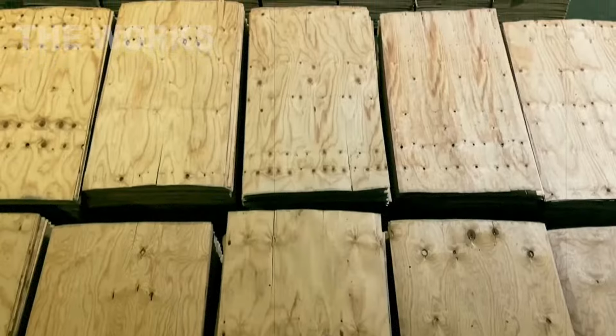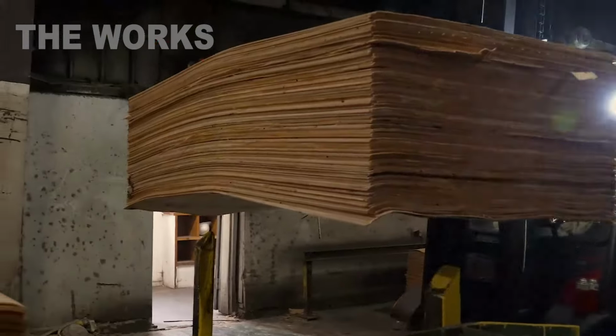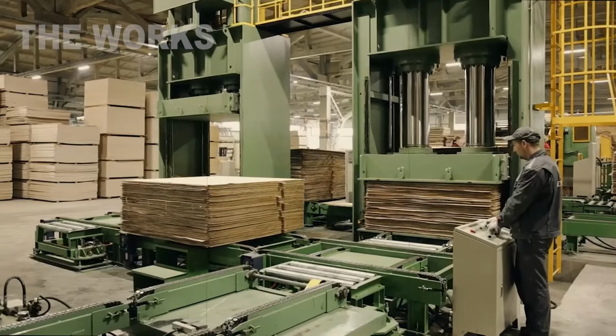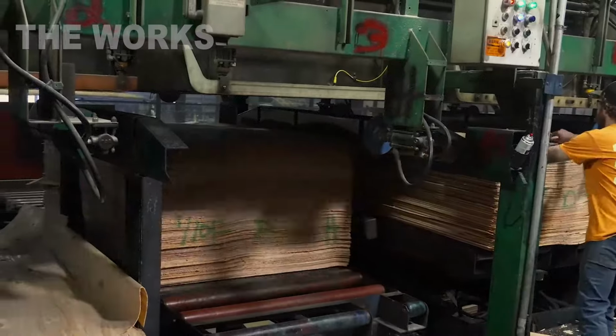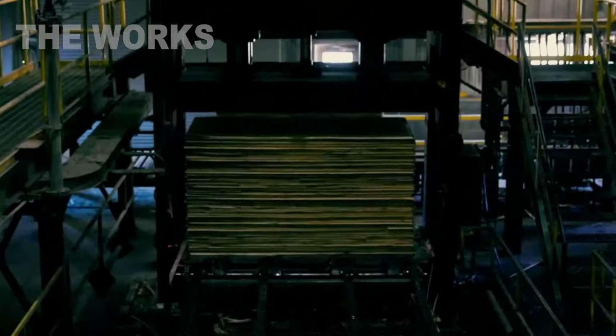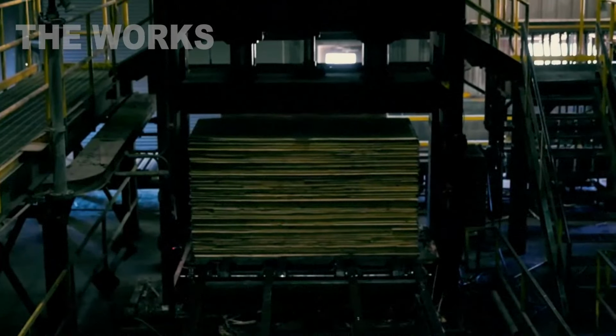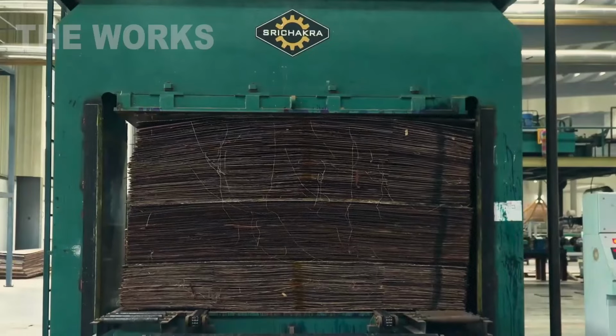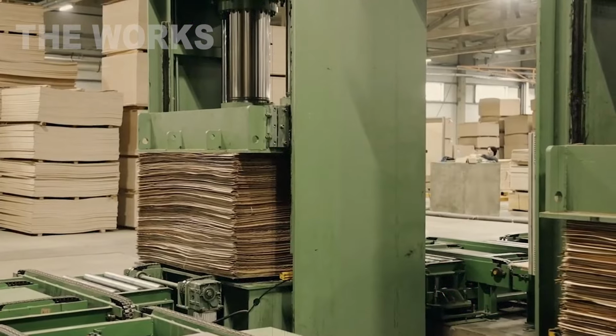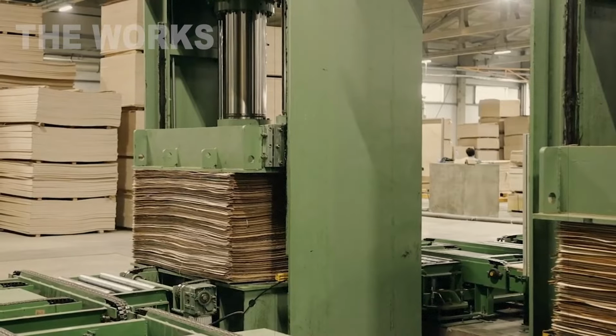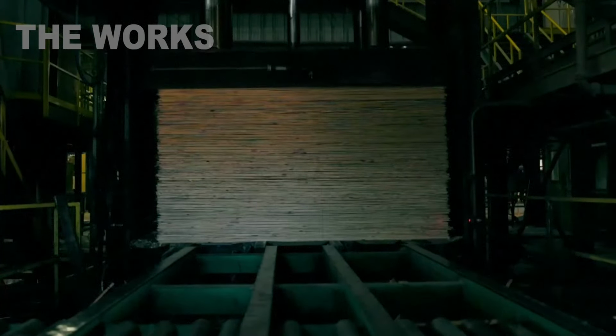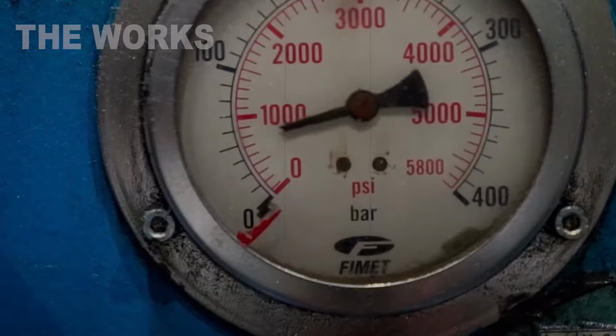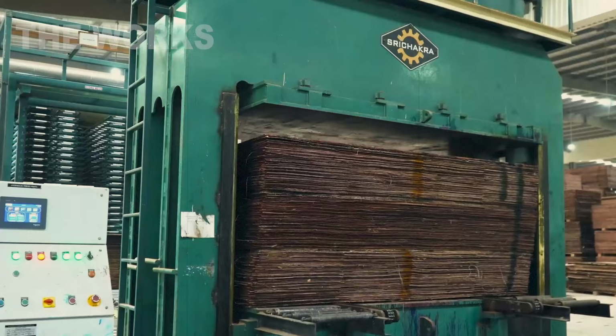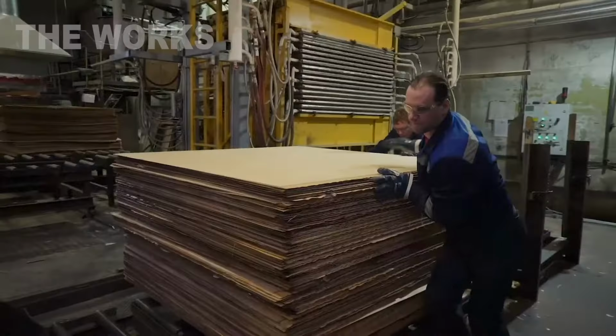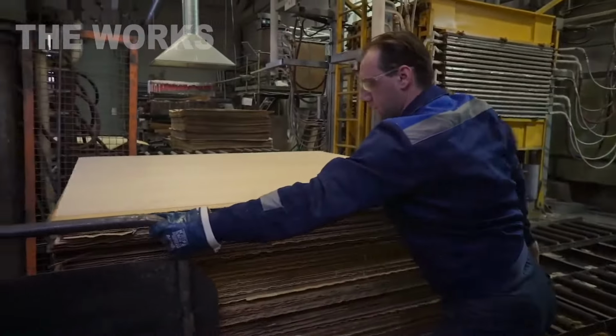The formed layups of veneer are fed to the most powerful section of production, the hot press. This is a giant multi-story structure, between whose plates several dozen future plywood sheets are loaded simultaneously. With an enormous force reaching tens of kilograms per square centimeter, the plates compress the veneer layups. At the same time, the plates are heated to a temperature of 150 degrees Celsius. Under the influence of high pressure and temperature, the glue polymerizes, permanently bonding the layers into a single, incredibly strong monolith.